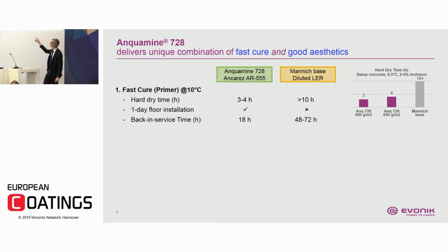So the benefit of this 3 to 4 hours versus 10 hours is a massive benefit. You can actually apply the second coat on the same day, and that gives you a true advantage in using that system. You can apply, so back in service time is 18 hours. If you do a top coat on it and that cures within 12 hours, then the next day, Monday morning you apply, and Tuesday morning you can actually walk on the system.